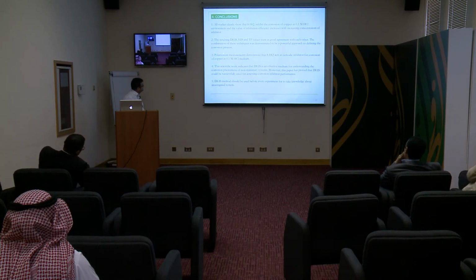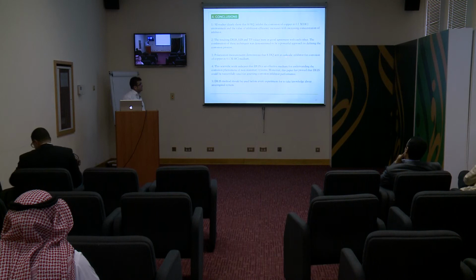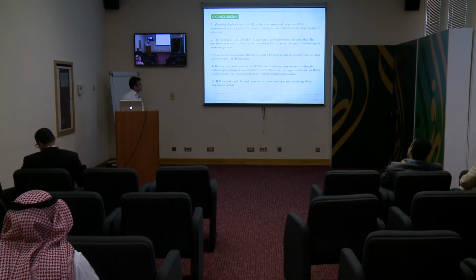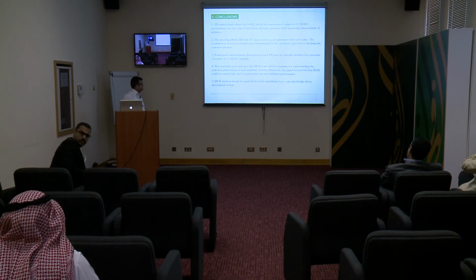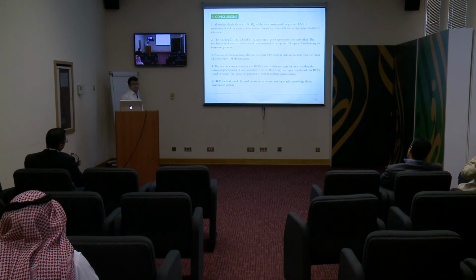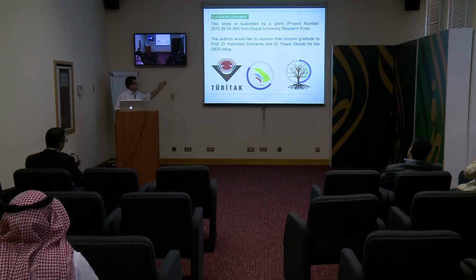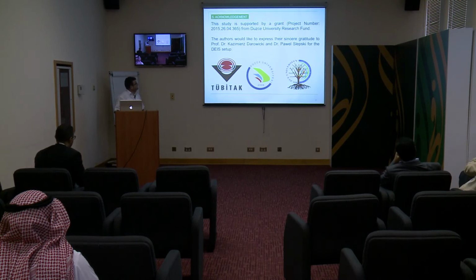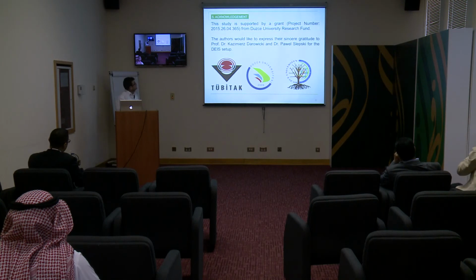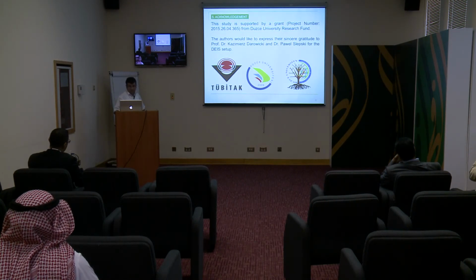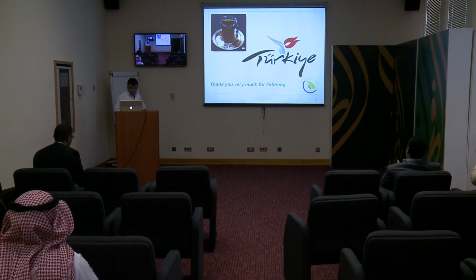And the polarization measurements demonstrate that they act as cathodic inhibitors, and this scientific work indicates again an effective measure for understanding corrosion phenomena of non-stationary systems. Moreover, this paper has proved that this method could be successfully used for assessing corrosion inhibitor performance, and this method should be used before every experiment, before Tafel, to gain knowledge about the system. The reference is a project which we took from the university, thanks to Professor Darowiecki and Paweł Ślepski from Poland. Thank you so much.